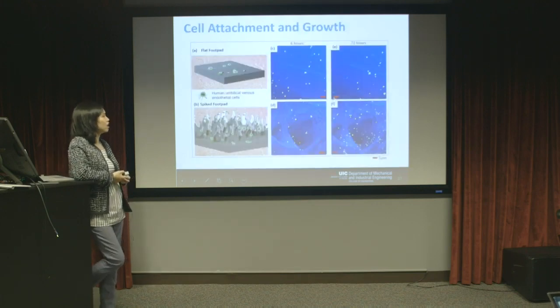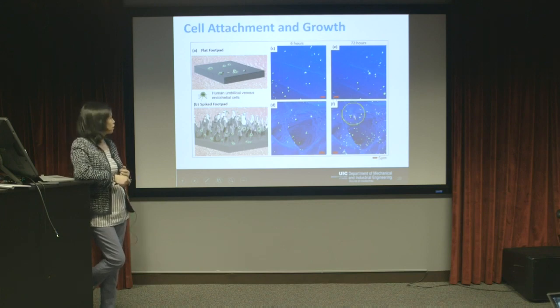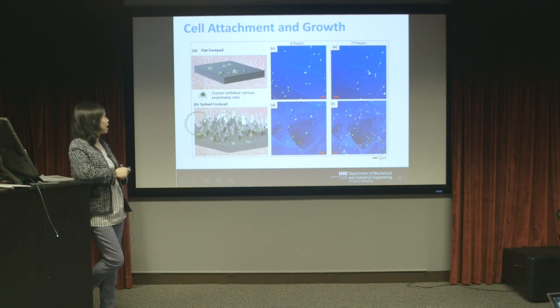And in addition to that, with the multiple scale feature of the foot, we found that it has unique benefit for cell growth and cell attachment. So this is a comparison of the flat foot pad and the spiked foot pad. In those 4 pictures, the green dots are fluorescent cells. We put some cells on the surface, and in the first 6 hours, we imaged them. You can see that there's no big difference.